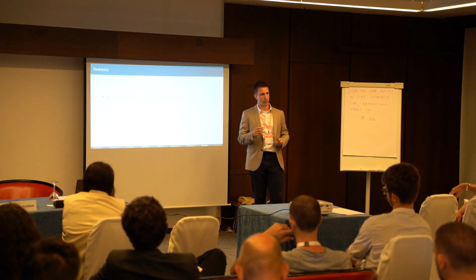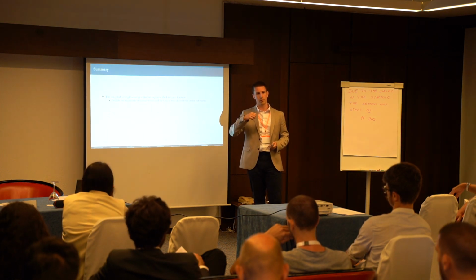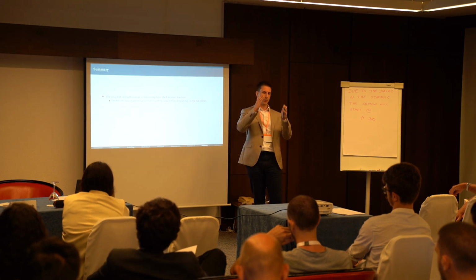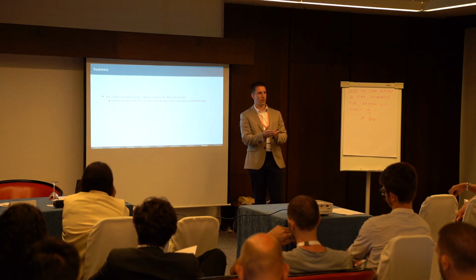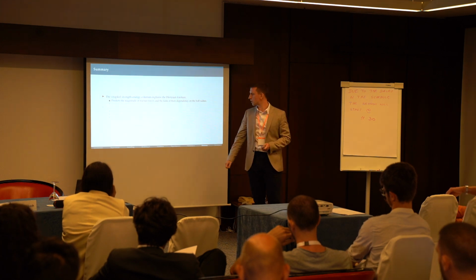Probably we just cannot ignore in some cases the residual stresses, and we need to include them in the model. And using this coupled criterion, we can explain why it's not at the contact radius exactly, because the force required to initiate there will be much higher than some optimal minimum farther from the contact radius.